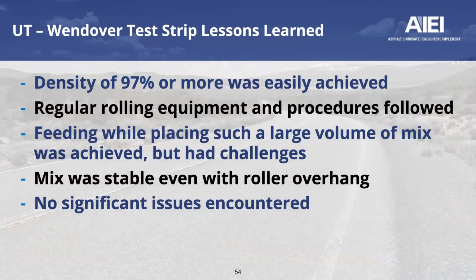What did we see at this test strip? Well, first and foremost, the target density in Utah is 96%. They were getting densities of 97+%. They were using regular rolling equipment. They did notice, as we saw in that one picture, that feeding material was a challenge to get enough material on site, even though in their case, remember, this was a zero haul situation. They definitely created a great plan for that next day.